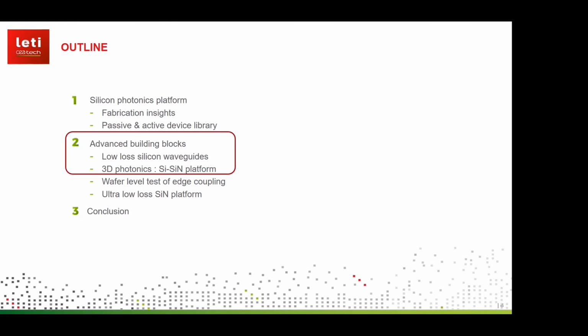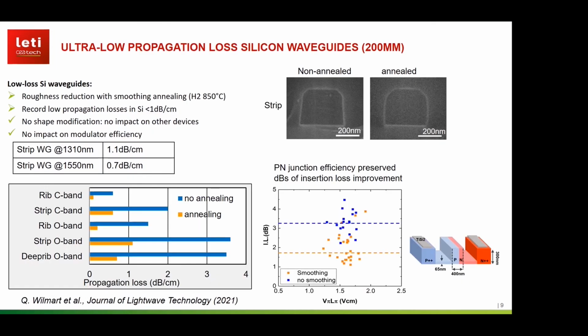Okay, so now the specific building blocks. The first one, I'd like to have a focus on the silicon waveguide. It's very basic, but it's important, I think, because we have developed a process to do smoothing of the waveguide in order to reduce the roughness, and it's very impressive in terms of propagation loss reduction. We can achieve propagation losses below 1 dB per centimeter, depending on the wavelength, for a strip single mode waveguide. If you have a look at the improvement without annealing in blue here and with this annealing process in orange, the improvement is very impressive. And so we have very low propagation losses for silicon waveguide.